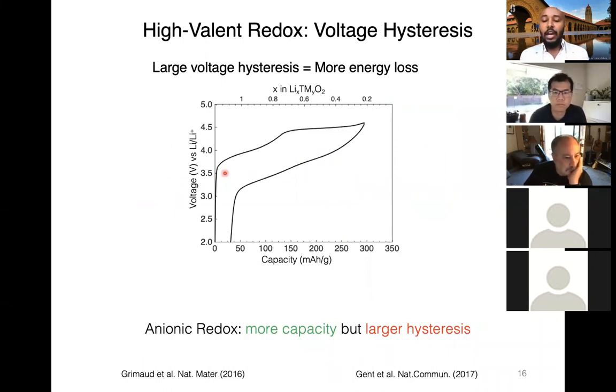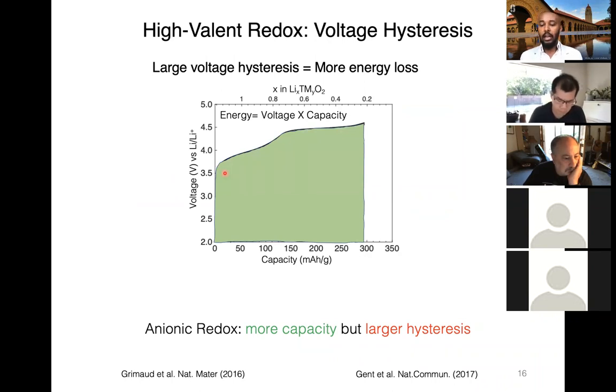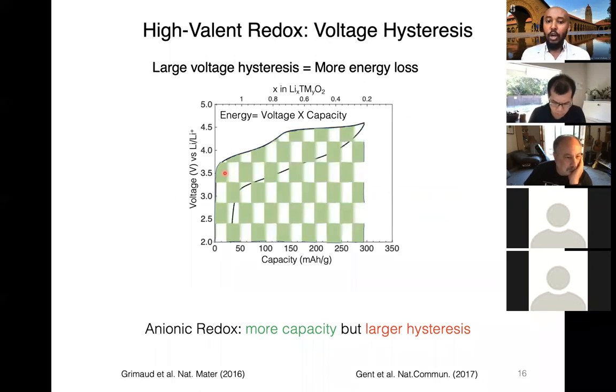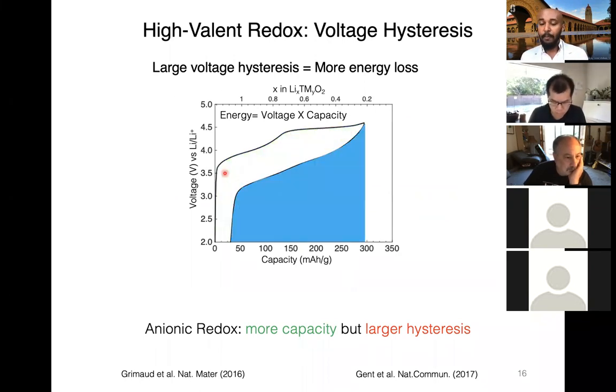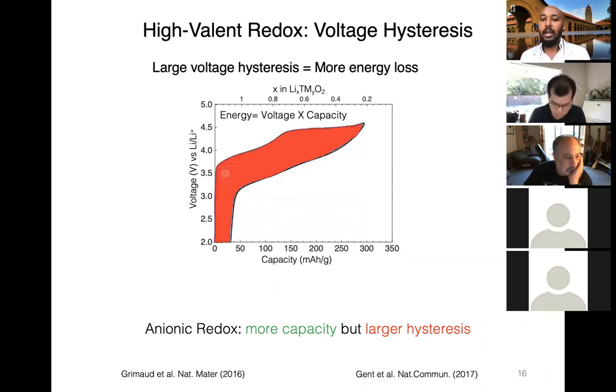So like I mentioned, energy we can store in a given material is given by capacity times voltage. In other words, the area under the curve is the energy we can store, for example. And here shown in green is the energy we can store. Shown in blue is the energy you can remove. But because of this large hysteresis, we have a dead energy shown in the red curve. Therefore, large hysteresis means we have more energy loss, and that's not favorable. So anionic redox, even though it can improve capacity by almost twice, it also causes large hysteresis or energy loss that has to be addressed.